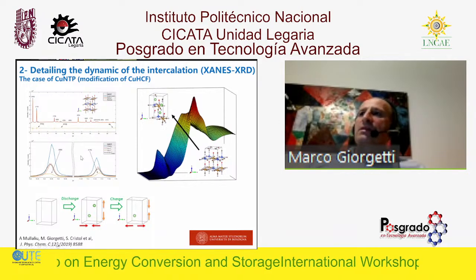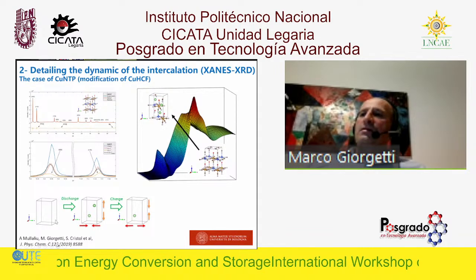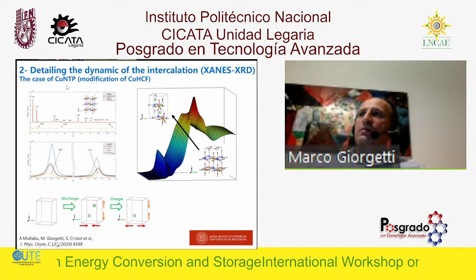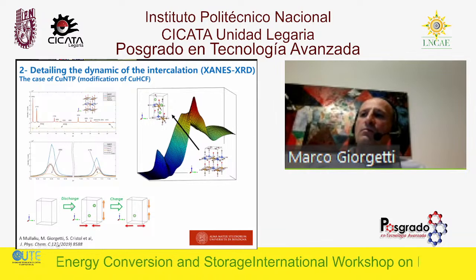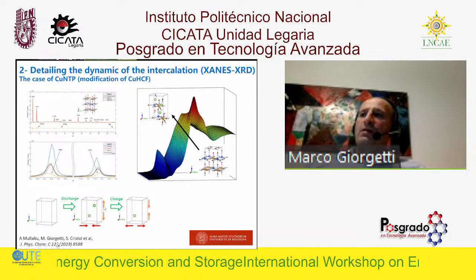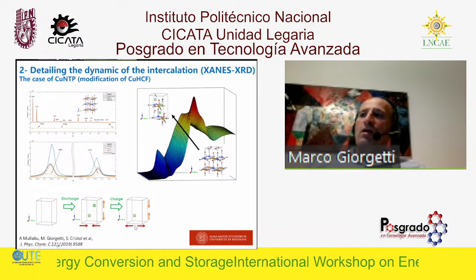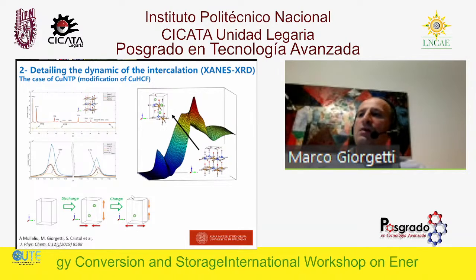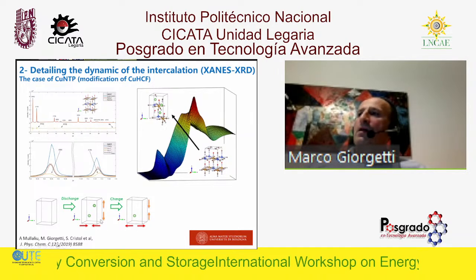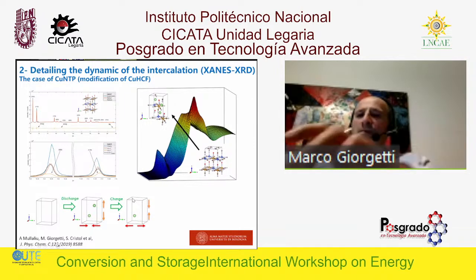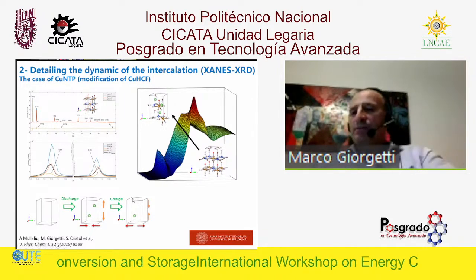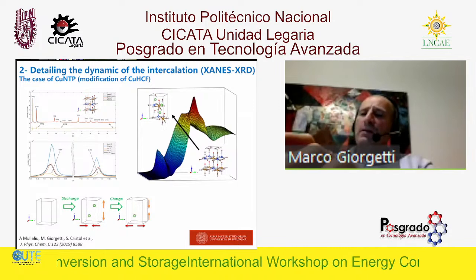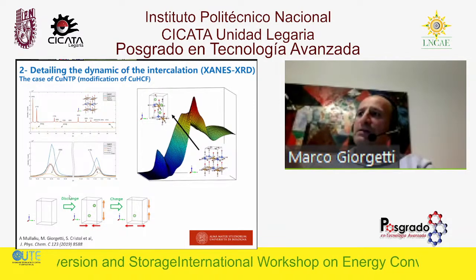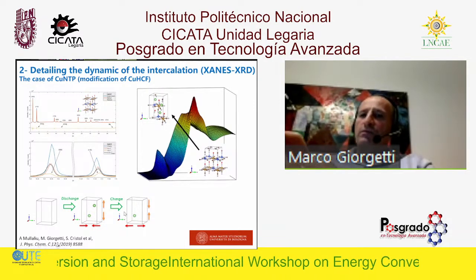The XRD basically indicated that if this is the monoclinic structure of copper nitroprusside, during discharge and charge, we have elongation, contraction, and also the opposite holds true during charge. So we can make a continuous loop on this. What about the milliampere-hour per gram? Not that great, but still there's a good sign for electroactivity.